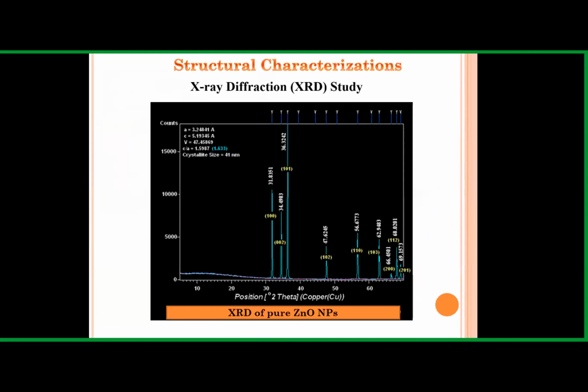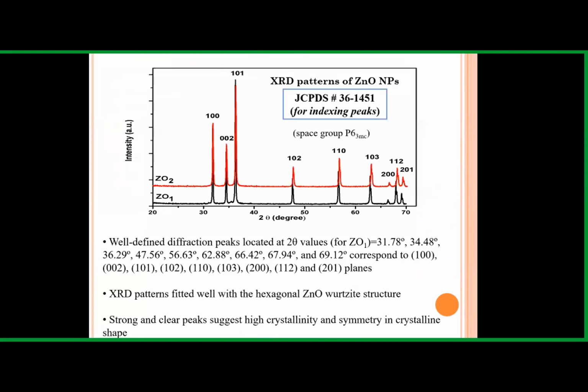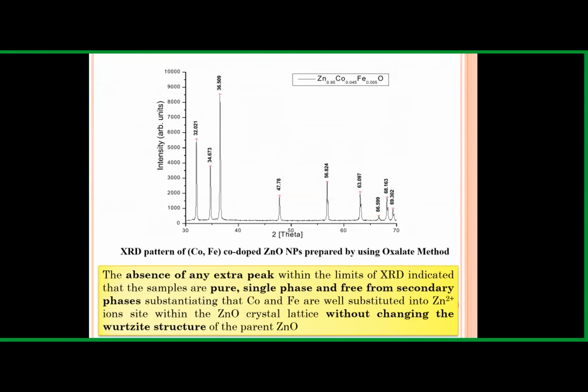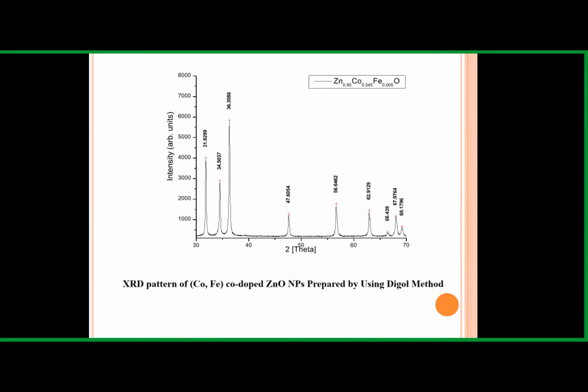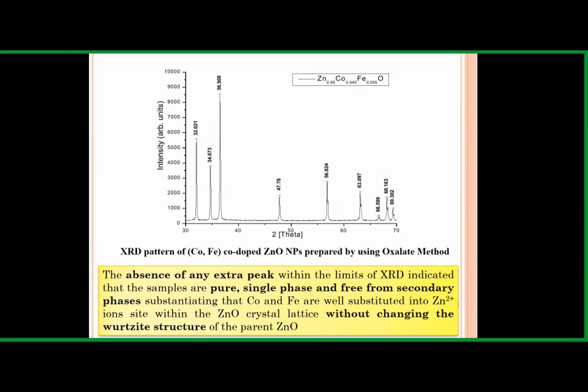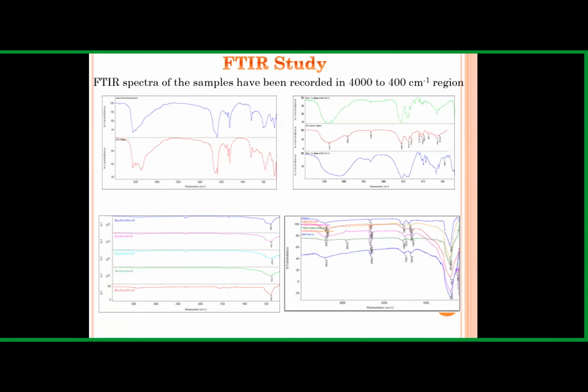Then the structural characterization was done using X-ray diffraction studies, and we can see that the X-ray diffraction of pure zinc oxide obtained from both these methods gives very good results with strong and clear peaks. This is the X-ray diffraction study of the cobalt iron co-doped sample, in which cobalt is 0.045 and iron is 0.005. The absence of any extra peak in both methods, the oxalate and the diglycol method, suggests that the samples were pure, single phase and free from secondary phases. So there was no change in the wurtzite structure of the zinc oxide.